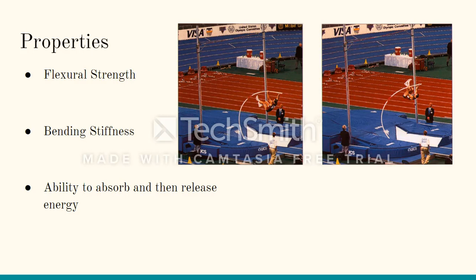Bending stiffness. The two materials used in the pole, carbon fiber and glass fiber, play two different roles in the pole. The carbon fiber gives the pole the stiffness, or quote-unquote springiness, as mentioned by a pole vaulter we interviewed, that allows the pole to quickly release the strain energy imparted onto it by the vaulter. However, releasing the energy too quickly can be problematic, and thus the glass fiber comes into play. The glass fiber allows for a much more even and controlled release of the strain energy, which gives the vaulter more time to achieve proper form while still allowing the pole to both absorb and release energy. This property given by the glass fiber is seen as more important than that given by the carbon fiber.